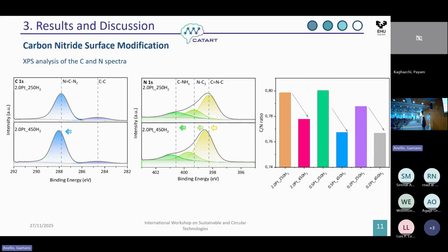Yeah. And also maybe it is a good point to examine the effect of pretreatment conditions, examining the reaction mixture. To treat the catalyst under the reaction mixture, because you have a reductive environment, independent of starting from calcined or other conditions. At the end of the reaction, the catalyst will be reduced. Yeah, actually, we also tried that, but we let this run for a long time at the reaction condition, and we know that not all the platinum was able to get reduced. We ended up with a mixture between platinum 3 or platinum plus 2.